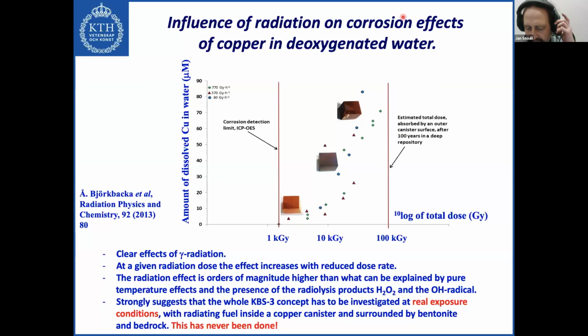So if I may, I have just one quick question, because it's very interesting that, if I understood it well, at the beginning the diffusion proceeds in zero-valent atoms of these elements, but then they can form some new phase, whatever, oxidic or sulfidic. So in that case, we could block a bit this grain boundary. So in fact, even if we have this very quick diffusion at the beginning, it could decelerate quite significantly in time. Do I understand well? If you mean if the oxides or the sulfides block the grain boundary? Yeah, the grain boundary. Okay.